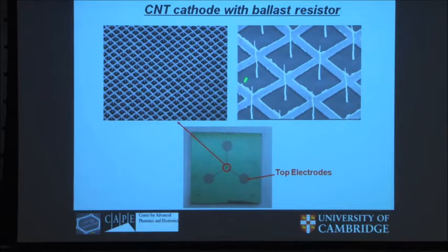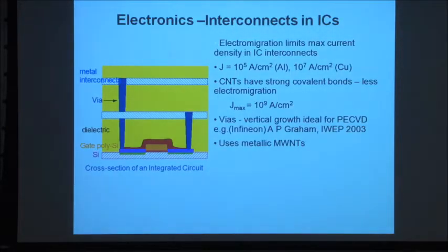And in this case, it's the same similar thing as previously with individual nanotubes. In this case, they have to have series resistors to limit the current coming out because of the high current densities. But this is really quite close to being very useful. So that's all I want to say about field emission. It's potentially really one of the more interesting applications for CNTs.